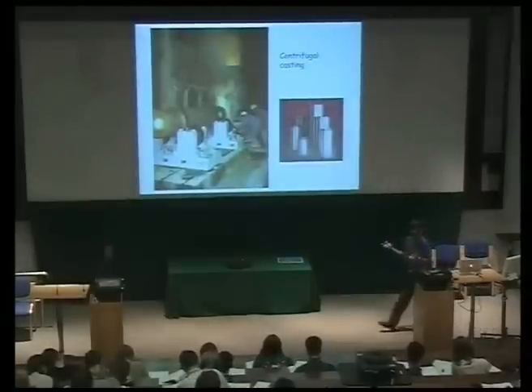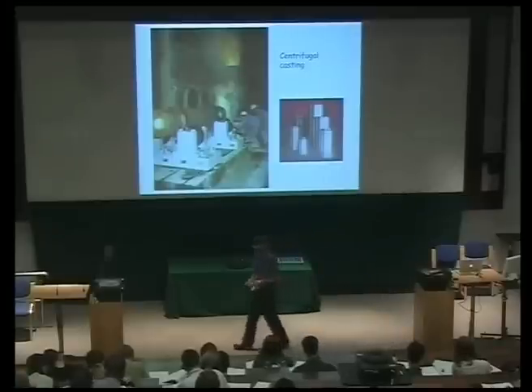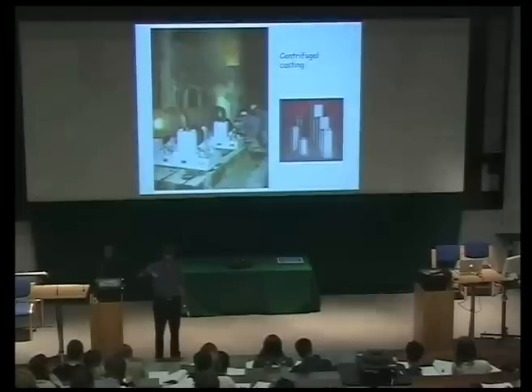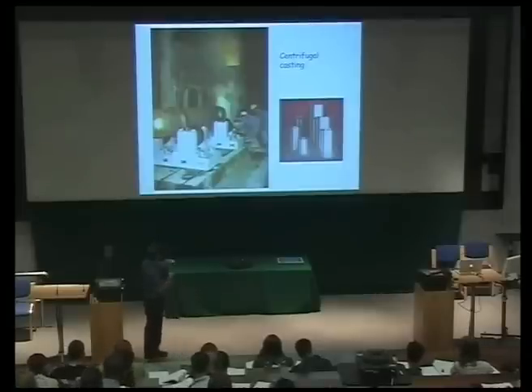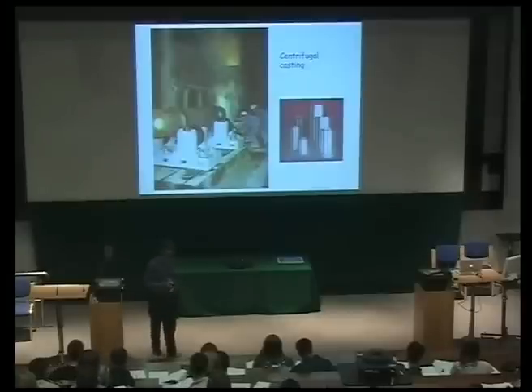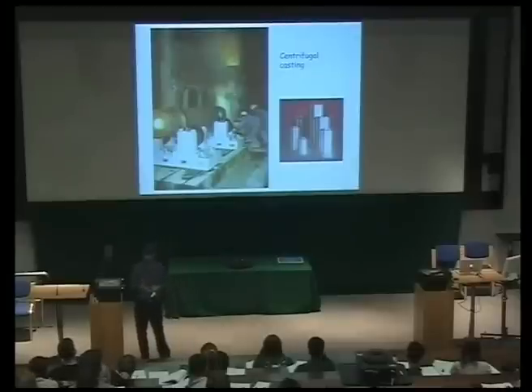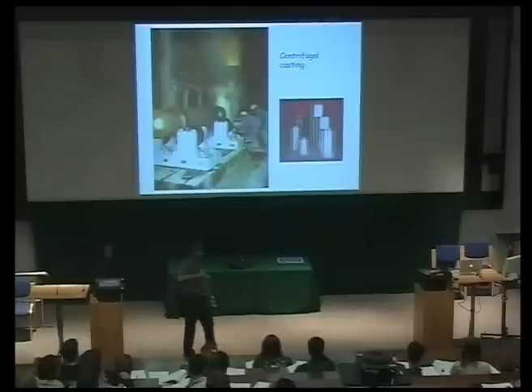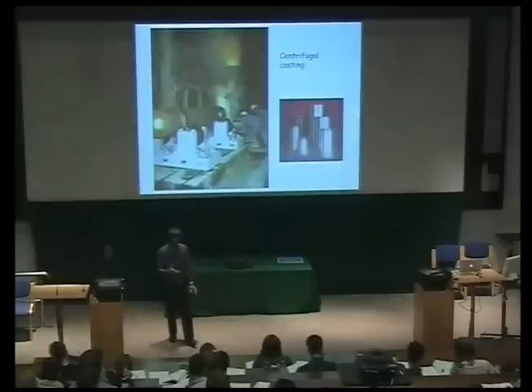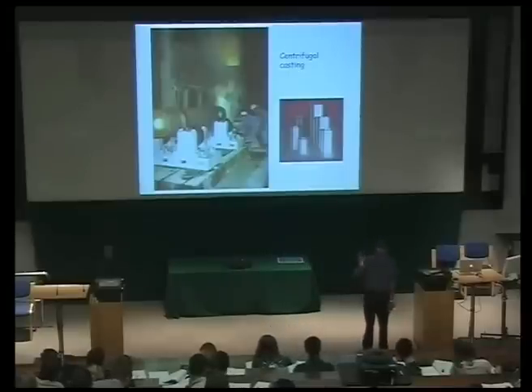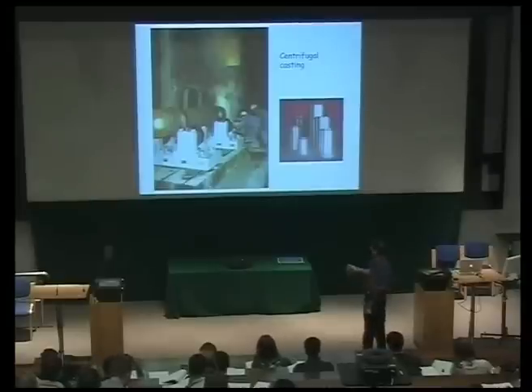This is a really spectacular technique where you make large tubes by a process known as centrifugal casting. You have a cylindrical mould which is rotating, and then liquid metal is poured into it — you see enormous fireworks-type operations happening in a real factory. The point is that you produce tubes; you don't have to drill those tubes and you can make them on a very large scale with very little waste material. Also, because the mould is turning at high speed, you get good homogeneity inside your centrifugal casting, so chemical segregation effects are minimised. A large number of the pipes and tubes used in chemical plant for aggressive processing are made using centrifugal casting.